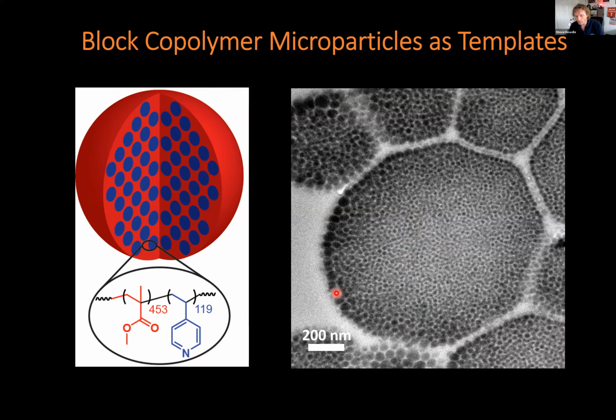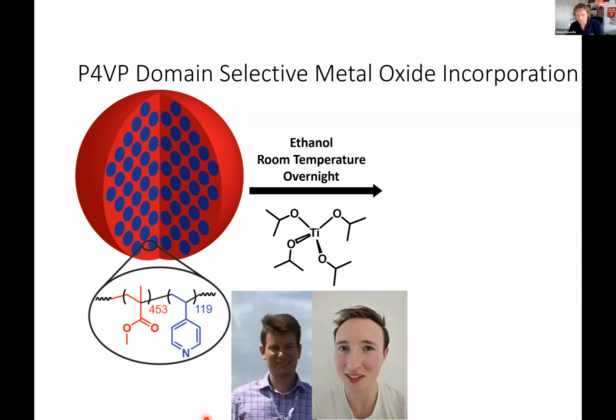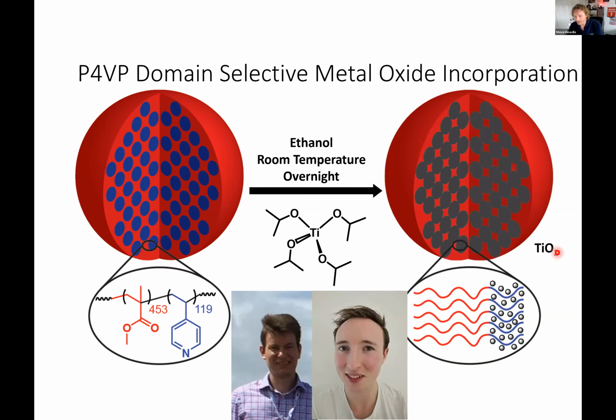This forms a zone where there's a lot of nitrogen groups present. Because of that, we can now add some titania and infuse this into the polymer particles. This is work carried out by Tom Bennett and Ryan Larder, who's currently writing up his PhD thesis. We made block copolymers with the idea of infusing titanium isopropoxide into the N-carrying blocks.